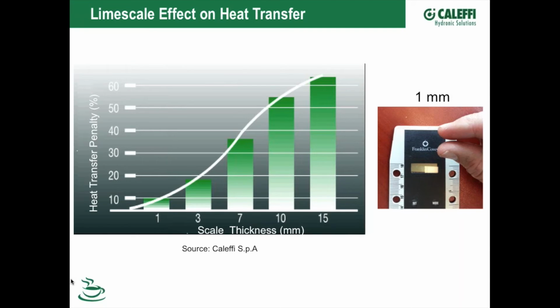So if you're selling your customer high efficiency equipment and you're putting this type of water in there, you can see what kind of penalty you're taking. That's going to show up in operating costs of that equipment, and certainly longevity of it. If you start putting hot spots on that heat exchange surface, that's where you burn through. That's where you get problems with pinholes and boilers failing. So anything else on that, Mark?